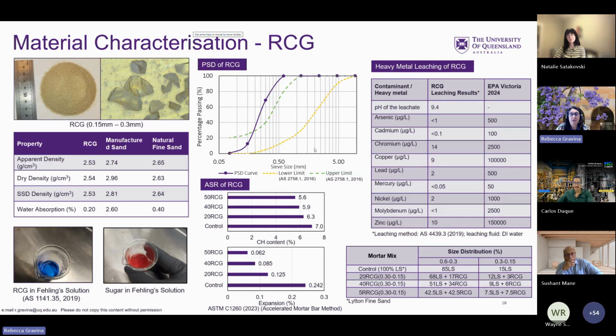Other work that we've been doing is in terms of the ASR, alkali silica reaction performance of recycled crushed glass at different percentage replacements within the mix designs up to 50%, and also the leachate properties of the material. So that's helped us inform up to what percentage replacement we will put recycled crushed glass into those mix designs.